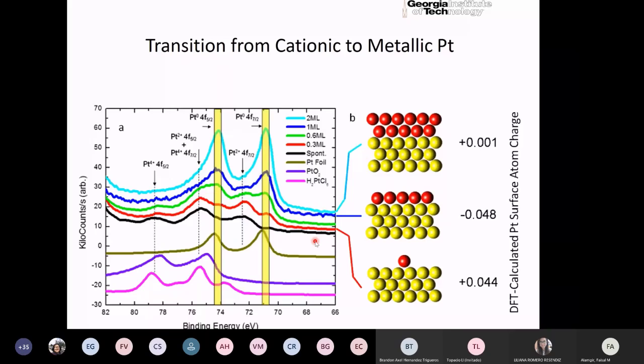So if I look at the summary graph here, you can see that the overpotential, that is the reaction potential for the oxidative versus the reductive reactions, that difference, the smaller it is, the better it is for the catalyst in a fuel cell. And that value is smallest when we have platinum monolayers grown on graphene with nickel on the other side. And it's better than platinum on graphene without nickel, or basically with nothing on the other side. And as a control, we compared it to gold on the other side, and gold is supposed to make things worse, and it does. So we are able to get this electronic effect through the graphene in a real catalyst.